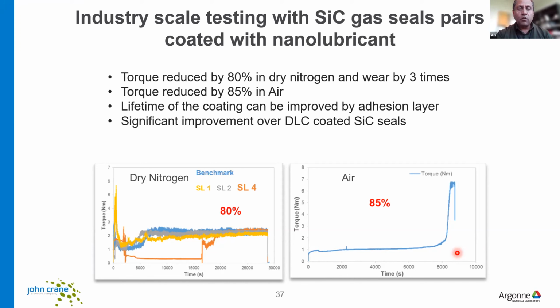But towards the end, what actually in the real practice, when they do this testing, silicon carbide seals against silicon carbide seal, coated with this special lubricant, what we have seen is the torque is reduced by 80% in dry nitrogen, whereas in case of air, it's 85% reduction. So this is a significant improvement. And then the adhesion, of course, needs to be improved, and that is easily taken care of by an adhesion promotion layer. But this is a significant improvement over the DLC coated silicon carbide seals.